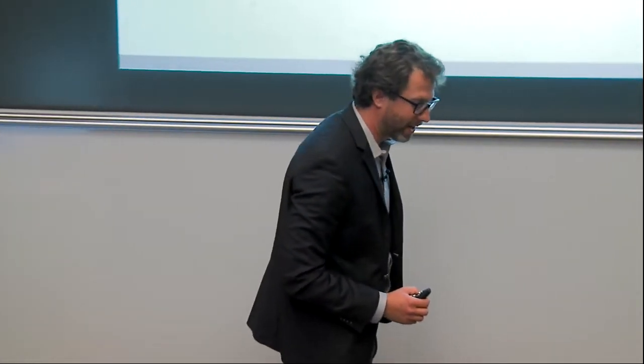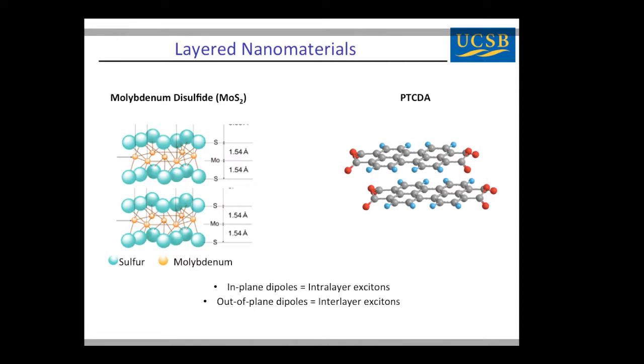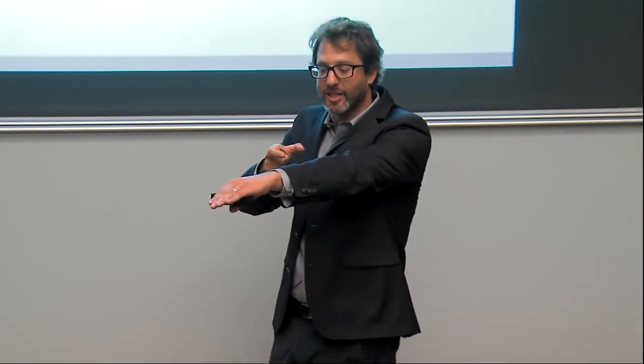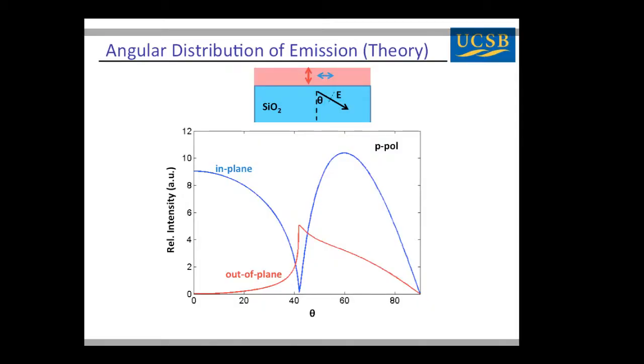What I want to talk to you about is comparing two layered systems, so systems where we start with a planar constituent and stack them, okay? So we'll talk about molybdenum disulfide, where we have a weak interlayer coupling, versus an organic system where we have strong interlayer coupling. And now the idea here is that these anisotropies are going to relate to distinct excitations. So an in-plane excitation, right, we would call something like an intralayer exciton. It's happening within one of these layers. We want to see if we can compare, by looking at anisotropies, these in-plane excitons to an out-of-plane oriented dipole, something that we would consider a between-layer or interlayer exciton, something where we separate the electron and hole between layers. So that's the idea, right? So we would look at two different orientations of the dipole.